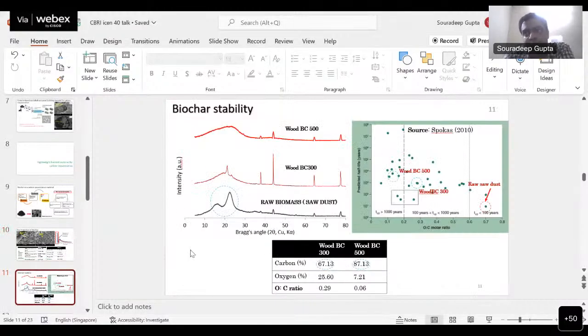But the question when it comes to bio-based building material is how stable it is. Because we have seen that if we use the raw biomass feedstock, there are a lot of durability problems because they are not stable in the highly alkaline environment. So we did this XRD investigation to see the decomposition of different sugary phases or polysaccharide phases in the biomass at different temperatures. And as you can see from this signature of raw biomass, there is a broad hump and a sharper peak, which correspond to cellulose and poorly crystalline polysaccharides and hemicellulose. And as we prepare biochar at 500 degrees, there is a broad hump formed, eliminating both these peaks, which means that both cellulose and the sugary components have completely decomposed.